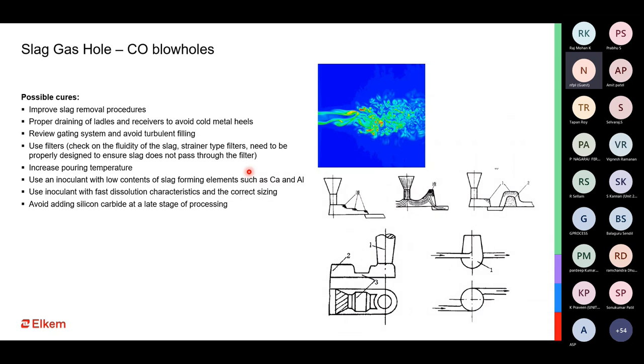For example, if you're using a high magnesium ferrosilicon magnesium, you would have a much higher tendency for slag generation, because higher magnesium means more turbulence, more reaction, and thereby more slag generation. The same can be said about calcium and aluminium. If your treatment alloys have high aluminium and high calcium in the system, there can be a strong tendency of excessive slag generation. So we have to make sure that we choose our inoculants and ferrosilicon magnesiums in such a manner that they do not cause excessive slag in the system.